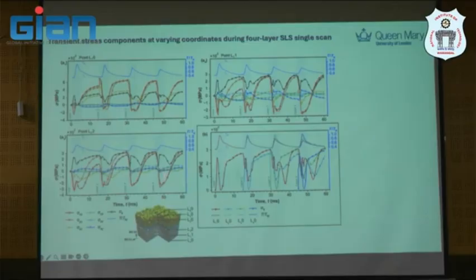And if you vary the location as well, I mean, this is a different stress component, you will see that even the shear component here you can extract. And they behave differently from the principal or normal components. So quite interesting and gives insight. And this is difficult from a neutron diffraction or diffractometry perspective. If you want to rotate your sample to the shear component, it's quite hard because you need a rotating table that allows you to move for a certain angle to do that. But anyway.